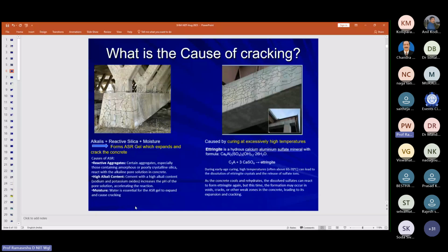In the case of the bridge supporting system, that is the piers, the cracking was ultimately found to be due to the alkali-silica reaction. That means the alkalis present in the cement react with the aggregates, reactive types of aggregates actually. Then in the presence of moisture, the alkali-silica reaction takes place, causes expansion of the system, and leads to cracking, which results in map-type cracking. Map type means it's an irregular pattern of cracking like this.